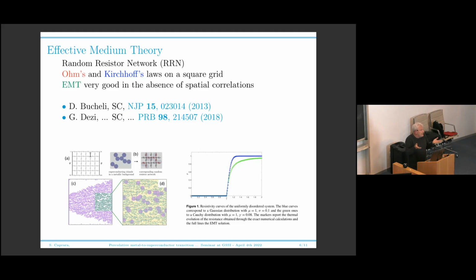This random resistor network is a linear set of equations. So you can solve this linear set of equations exactly numerically, because you take a rather large system. We usually took networks like 100 times 100 resistors or 200 times 200 to have a smooth solution. But this you can solve with some linear algebra library to solve Kirchhoff's and Ohm's laws on a square grid. Now, what we found, to our surprise at that time, you see here the points are the solution obtained within the random resistor networks, whereas the lines are the solutions obtained with the effective medium theory. The two fall one on top of the other if the disorder is fully random.